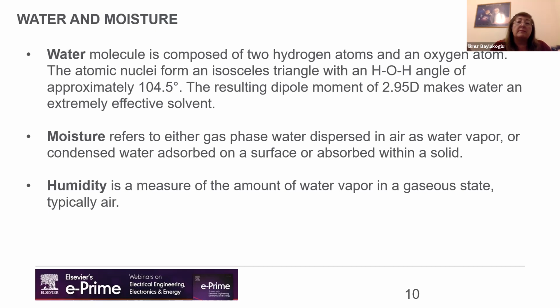So we talked about lots of failure mechanisms caused by water and moisture. We mentioned that water is our planet's most abundant material. But then what is water? What is moisture? Why can it affect materials so much? Actually, water is composed of 2 hydrogen atoms and an oxygen atom, and the atomic nuclei form an isosceles triangle with a hydrogen-oxygen-hydrogen angle of approximately 104.5 degrees. Its resulting dipole moment is 2.95, which makes water an extremely effective solvent. It can dissolve everything, actually.